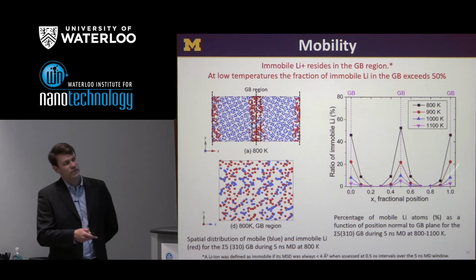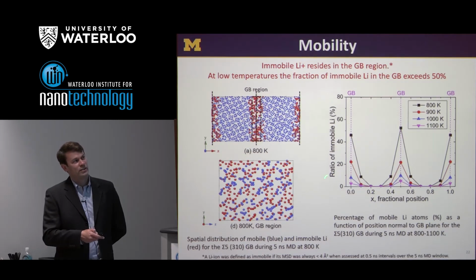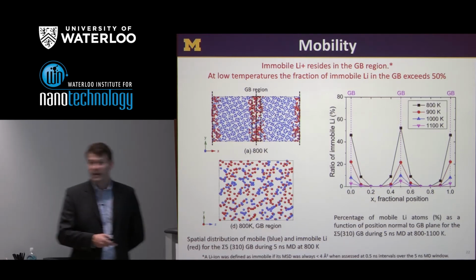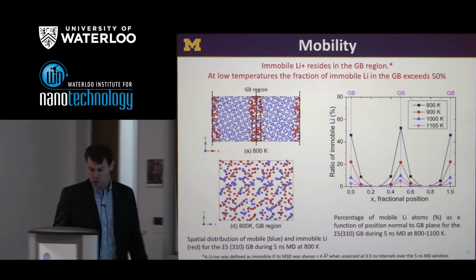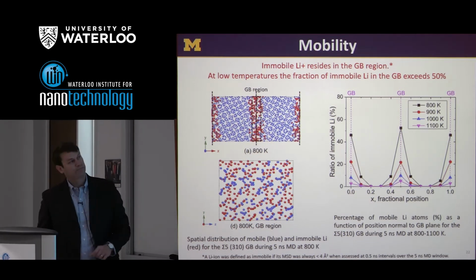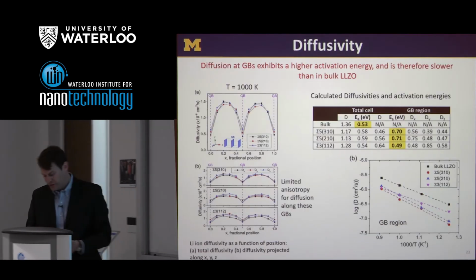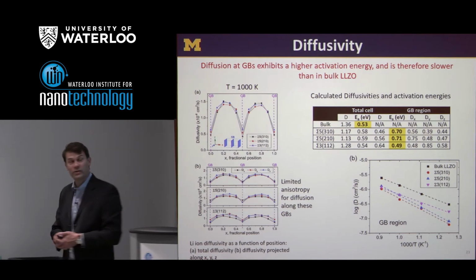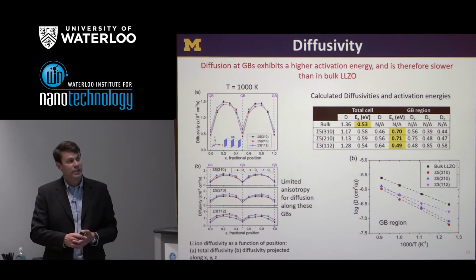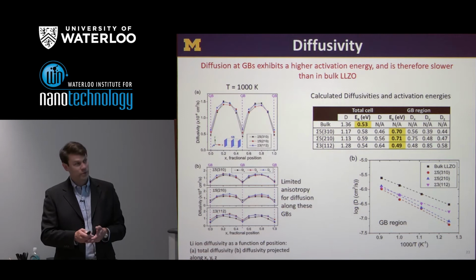And so this is a plot of basically the same thing, the fraction of immobile lithium as a function of position at different temperatures. And so you see these peaks here indicating a higher concentration of things being immobile in the boundary plane. So based on these qualitative pictures, we already expect there to be some degradation in lithium ion mobility in the grain boundary region.